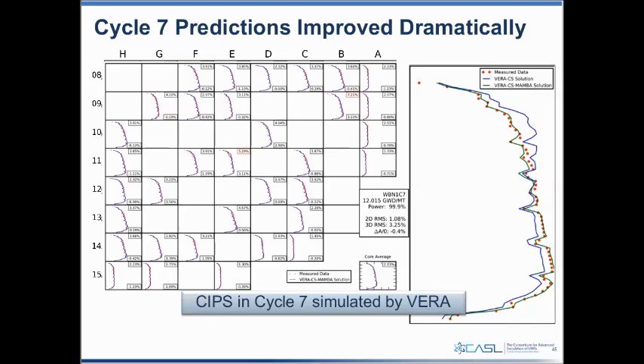Provide a little bit more information also, as Kevin had talked about. When we did the simulation simply with the impact CTF linkage without modeling crud, clearly in cycle 7 we saw some substantial differences in axial power distribution because CIPS was actually occurring there, but we weren't modeling the effects of that. When we include the effect of CIPS by adding Mamba to the simulation, you can see we get much, much better agreement in axial power distribution throughout the core.